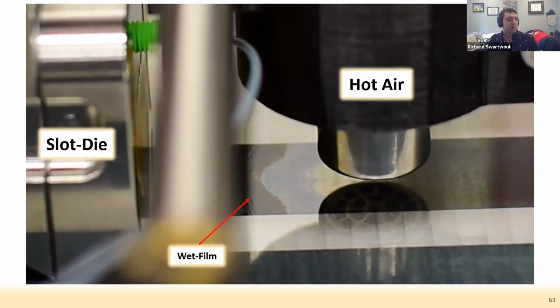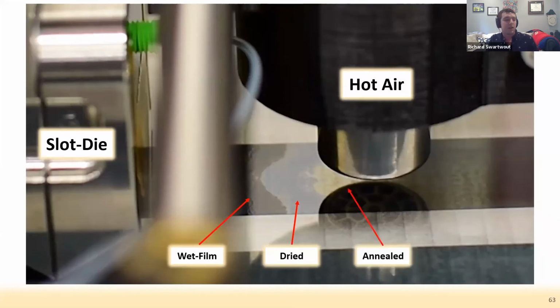The wet film is coated here. It's a little dark. It's a 25mm stripe width. It dries, creating kind of an interstitial phase. Then from the hot air, which is 120 degrees Celsius, it forms this annealed recrystallized phase, which has a bit of a gold color to it.